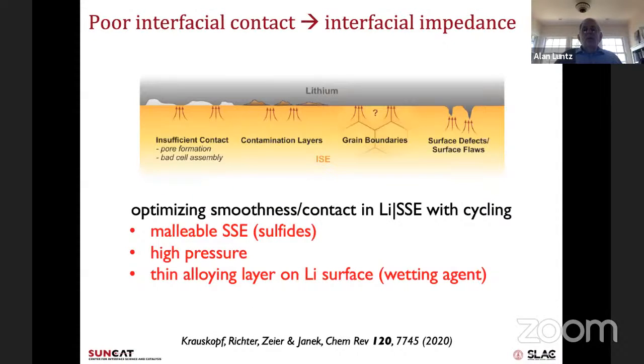So what about this poor interfacial contact? What can you do about that? I mean, there are all kinds of reasons you can get poor interfacial contact and these impedances. Roughening of the surface, contamination, grain boundaries at the surface, which are not as conductive, all kinds of defects. So how do you smooth this in cycling, as it tends to get worse when you cycle? Well, one of them is to have a malleable solid state electrolyte. The lithium's fairly malleable, but if you have a malleable solid state electrolyte, that helps, and sulfides certainly are. The oxides are not so much.